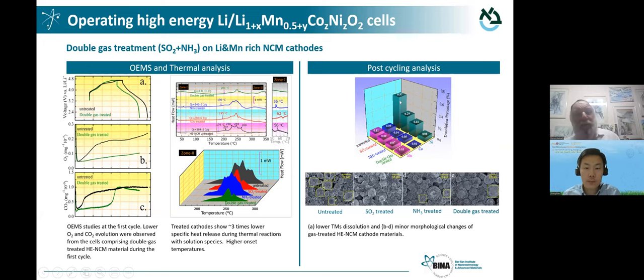So mitigation of transition metal cation dissolution is critically important, and we can see that. How do we measure it? After prolonged cycling, we take the negative, we extract the elements, and we can measure them. In fact, we can do quite fully quantitative analysis of the elements that moved and deposited on the negative electrodes. And we demonstrate that with our favorite, we have a minimal amount of transition metal dissolution and deposition. And by morphology, after post-mortem analysis, we always see that the particles retain their morphology. I would say that here we may win with these materials. Remember, the specific capacity we can reach with these materials is up to 300 milliampere hour per gram, which is very nice. And we can maintain stability.